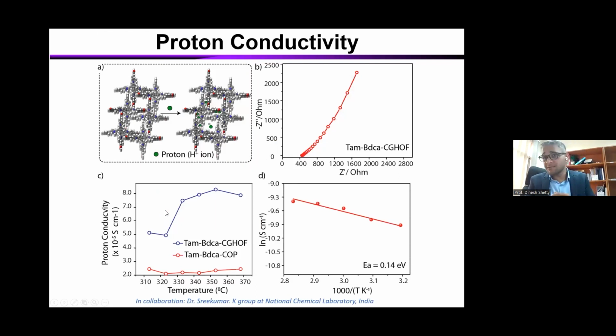Okay, what is the use of this? Because it's a hydrogen bonded organic framework, generally it is used for proton conduction, right? So we tested this proton conductivity. The interesting observation here is that if you have just COP, that's why tunability comes into play, look at the conductivity: there is at least a 4-fold increase in proton conductivity when we have HOF over COP. And another thing, the activation energy required for this is much less compared to the commercial Nafion membrane. For example, it's 0.21 electron volt, I guess. In our case, it's 0.14 electron volt.